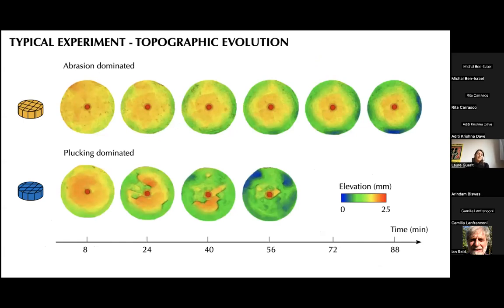So I show here two typical experiments, so the topographic evolution of two typical experiments. At the top, it was an experiment with a squared network. The network was spaced by 40 millimeters, and you can more or less see it on the topography, but on average, erosion is quite symmetrical, so it's a radial symmetry.